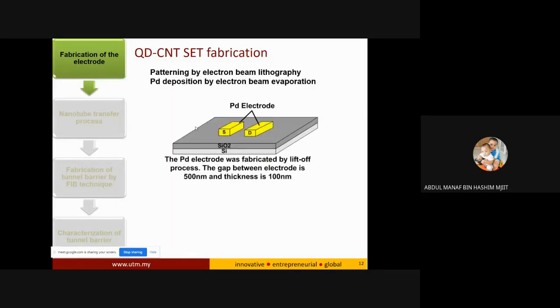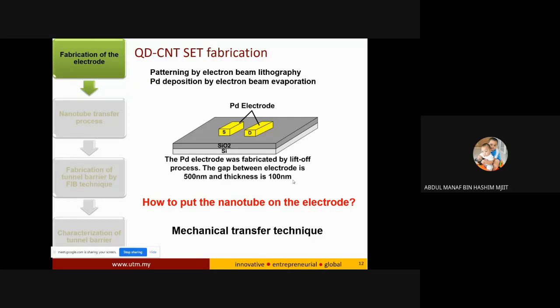So how do we fabricate it? First, we make a source and drain electrode using palladium. Of course, as I introduced, for the patterning of the electrode we use electron beam lithography, and for the palladium deposition we use electron beam evaporation. The gap between the source and drain is 500 nanometers. Now, how do we put the carbon nanotube on the electrode? Here we use a mechanical transfer technique.